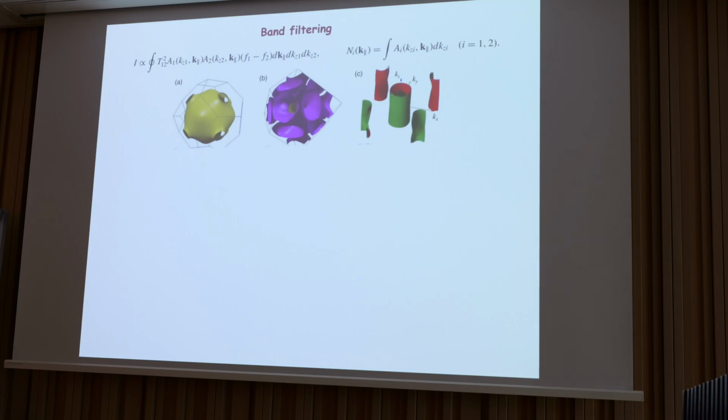Now, the materials that we are talking about have very different Fermi surface structures. So for pnictides, we already discussed that there are 2 basic bands, or maybe more, but they are oriented one in the center and then 4 in the corner. For cuprate, this is the most trivial Fermi surface, almost spherical in the center. And niobium is really a champion. It has an uncountable number of bands. I don't know exactly how many, 16, presumably, scattered everywhere across the Fermi surface.